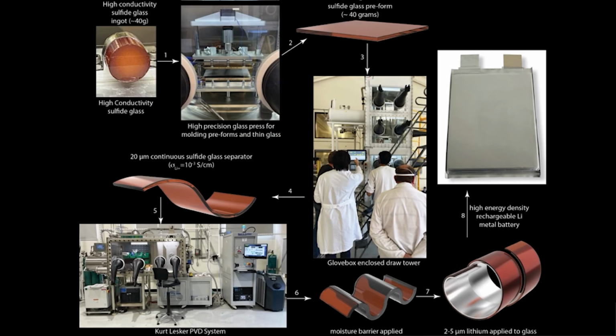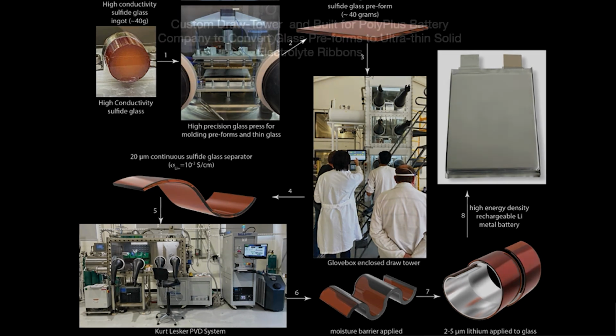And here you see roughly how we do what we do. We start with a high conductivity sulfide glass ingot that gets pressed in step 2 to form what's known as a preform that goes into our draw tower, which is in Berkeley, California. And then we draw it down to thin glass. That then goes into a PVD system where we deposit the moisture barrier and lithium.